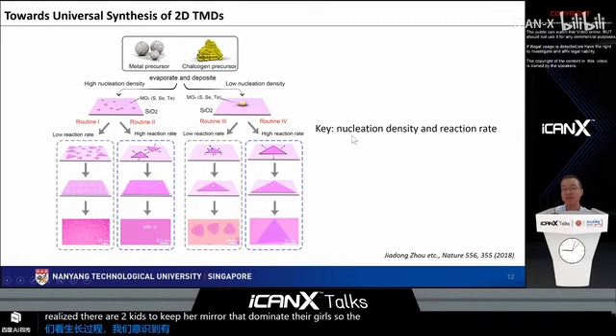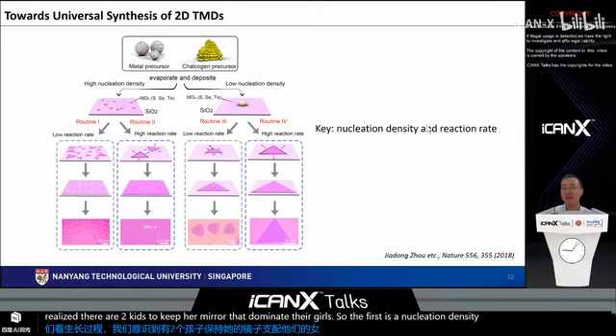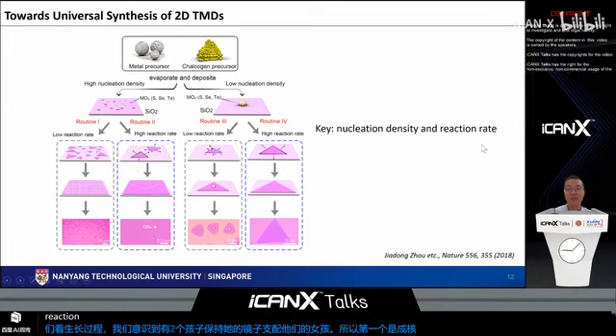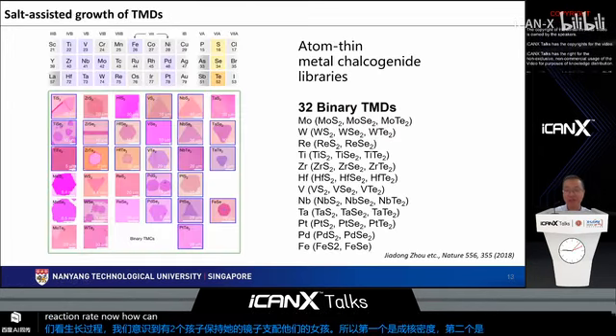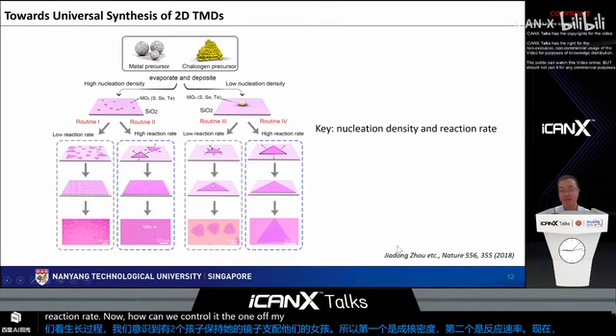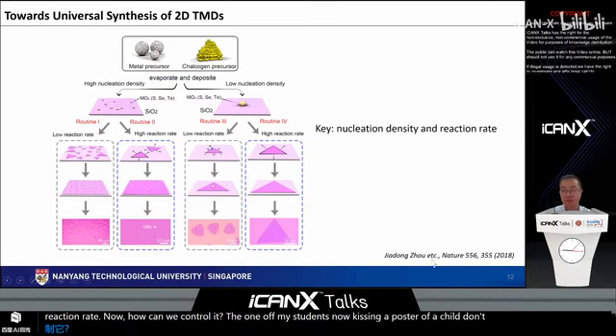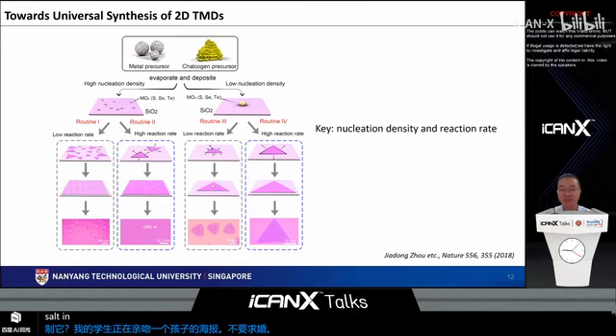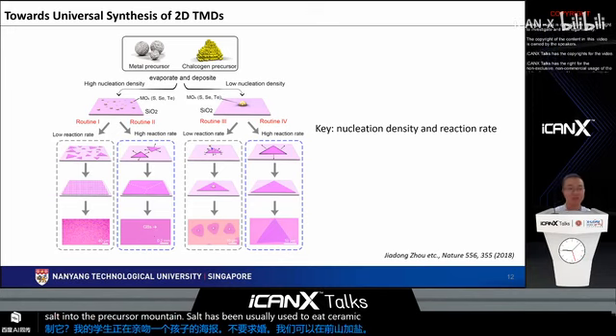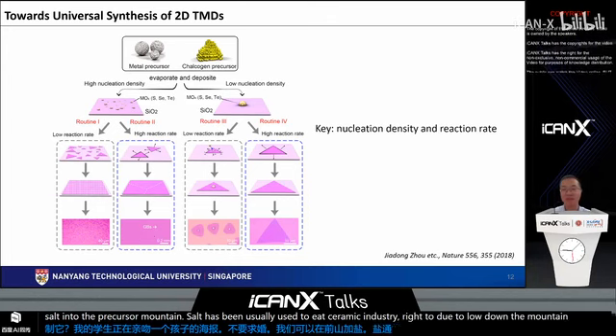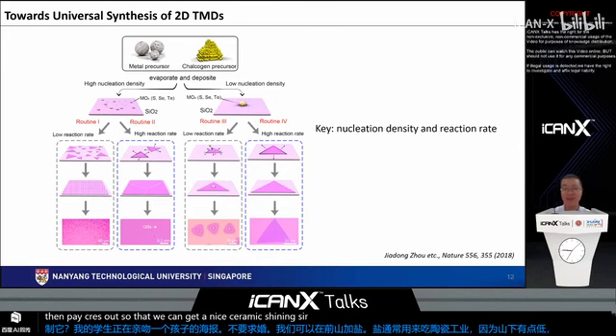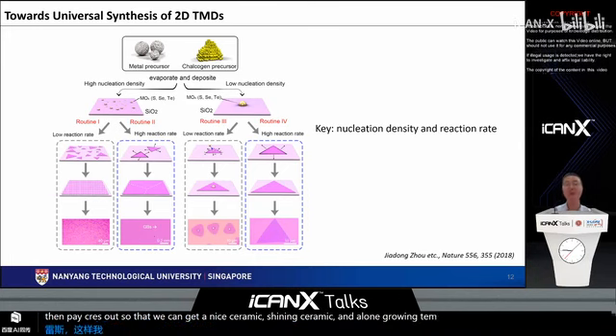So the first is the nucleation density, and the second is the reaction rate. So how can we control it? One of my students, my postdoc Jia Dong, proposed that we can add salt into the precursor. Molten salt has usually been used in the ceramic industry to lower the melting point of the precursor so that we can get nice, shining ceramic at a low growing temperature. So we borrow this idea for the growth of the 2D TMDs.